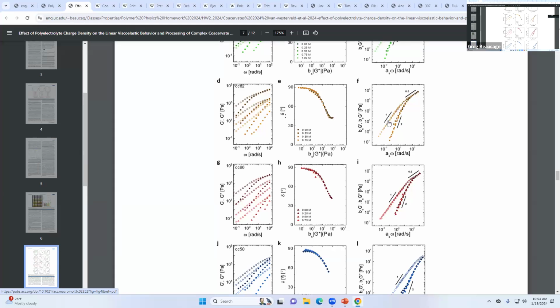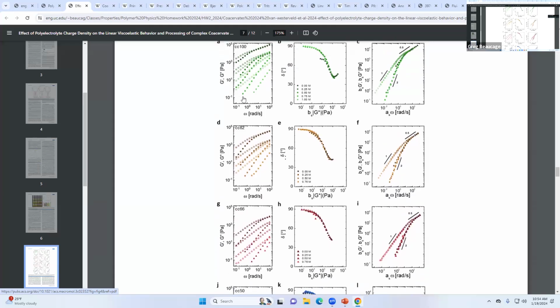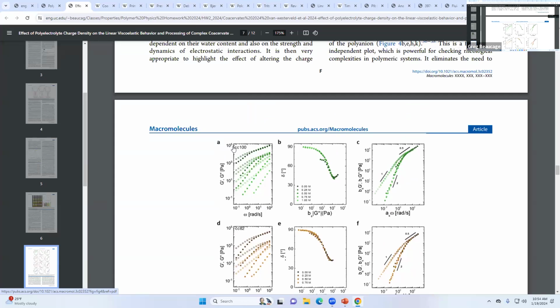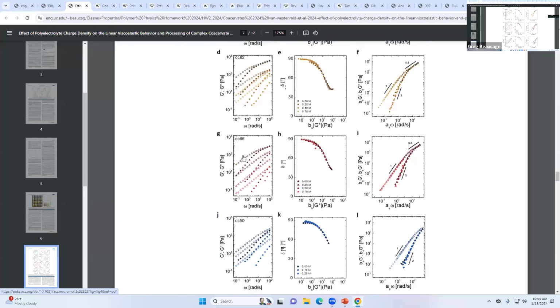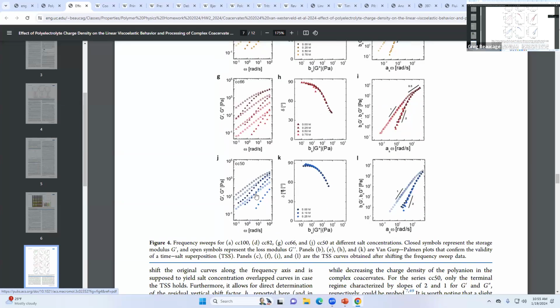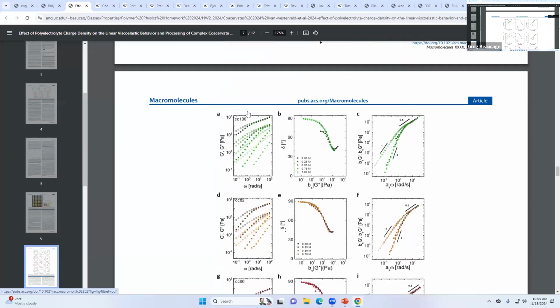Then the other thing is that these are at different salt concentrations. The cc100 means it's 100% with none of the PEO sides in the block copolymer, the polyanion. Then she reduces the amount of PEO in it, and the viscosity drops. And these are different salt concentrations. You can see the behavior changes as you add more salt. The top one is the least amount of salt, and the bottom one is the most amount of salt, and you get to this kind of classic behavior here.